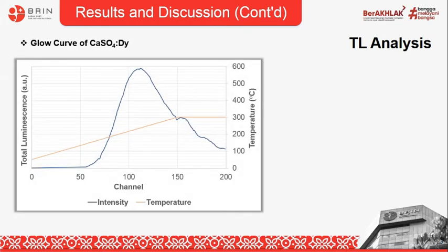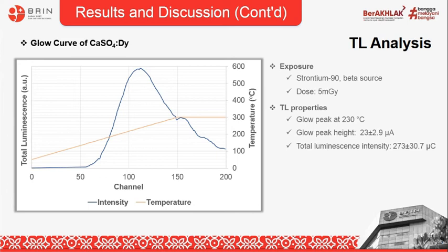The glow curve of the powder after irradiation by strontium-90 was shown here. According to the thermoluminescence test, the phosphor exhibited a maximum glow at around 230 Celsius degree. It confirmed the experimental results from previous studies that dysprosium-doped calcium sulfate phosphor has a dominant peak at around 220 until 240 Celsius degree. The phosphor stored 273 microcoulomb from the irradiation and generated about 23 microampere maximum current during the reading. This result indicated a significant improvement of calcium sulfate-based phosphor sensitivity compared to Kartikasari's work for an equal dose.